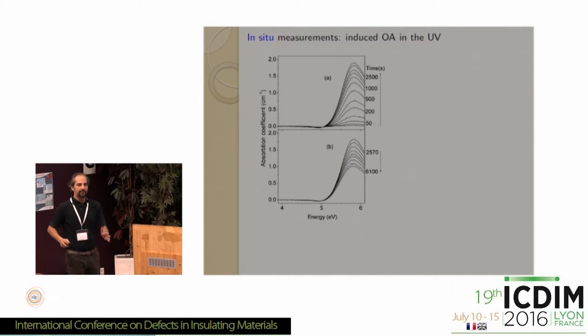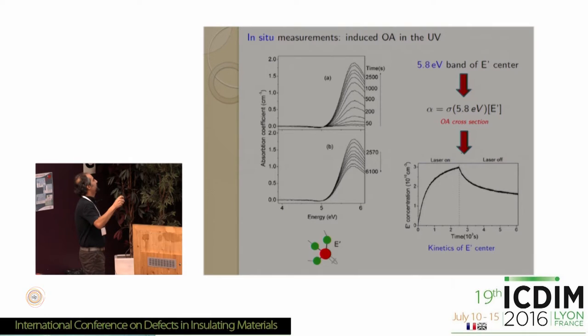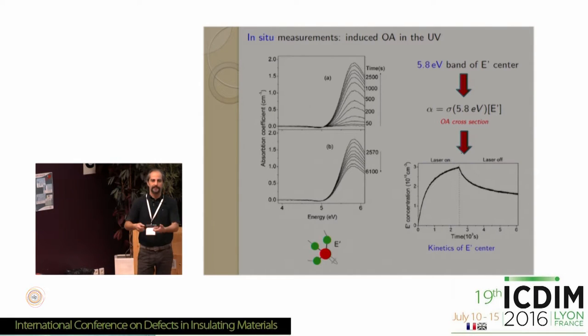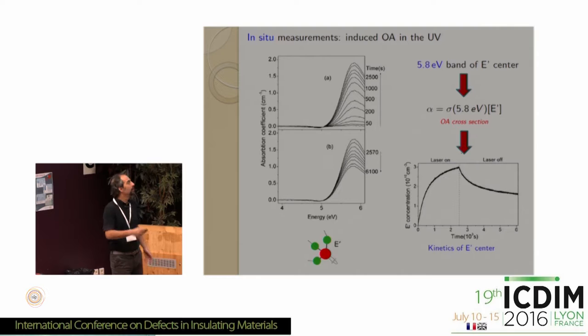When we turn off the laser, we see that this band begins to decay spontaneously, as seen in the lower panel. Now, this band is the known absorption band of the silicon dangling bond in SiO2. So, of course, this result means that the laser is capable of generating silicon dangling bonds in our sample. They grow, and then they decay spontaneously after the end of irradiation.